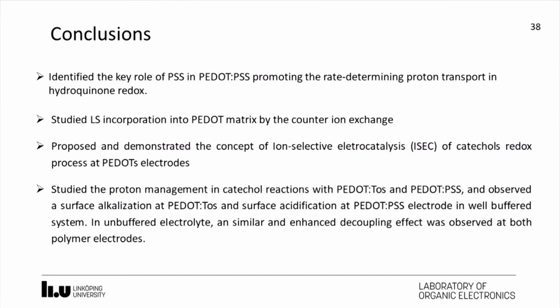So to summarize, we studied the key role of PSS in promoting the rate-determining proton transport in hydroquinone redox reactions. We studied the lignin-sulfonate incorporation into PEDOT and optimized the synthesis routes for large-scale applications. We also promoted and demonstrated the concept of ion-selective electrocatalysis of catechols in PEDOT:PSS electrodes. We have also studied the proton management of this reaction at the PEDOT electrode and observed a surface alkalization at PEDOT:TOS and surface acidification at PEDOT:PSS, respectively, in buffered electrolyte. In unbuffered electrolyte, a similar and even larger decoupling was observed.